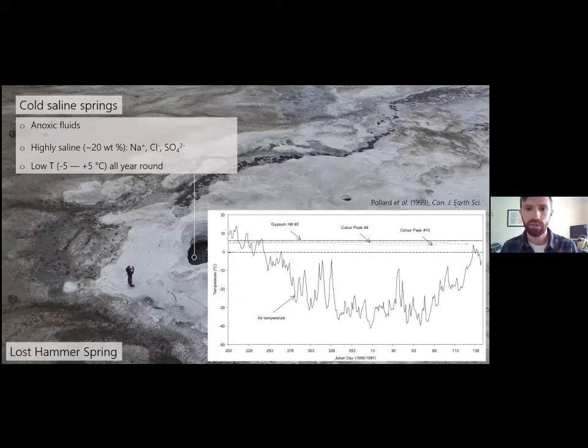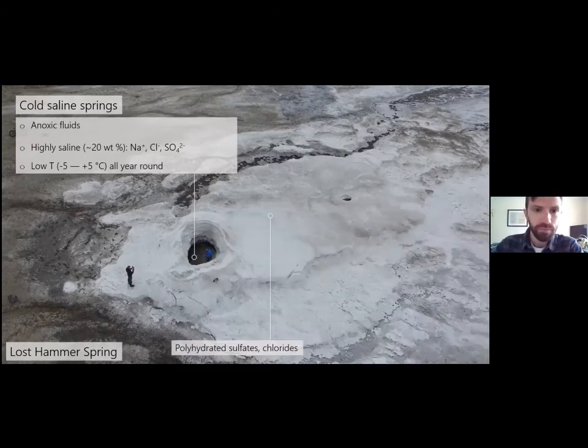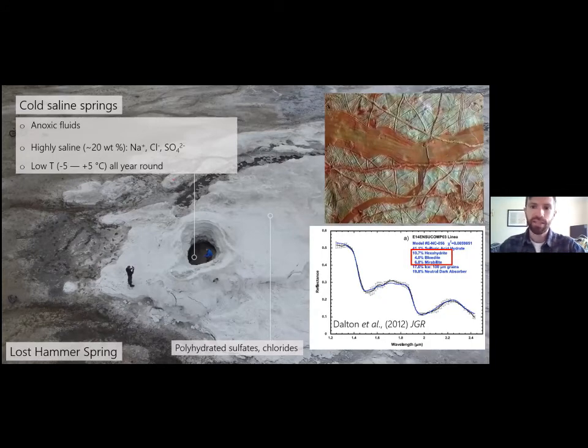The bottom line on this plot shows the Arctic air temperature, which gets as low as minus 40 C in the winter, but the spring temperatures remain constant and they resist freezing because of these high levels of salt. And the salts themselves are what caught our attention initially. These are polyhydrated sulfates and chlorides, things that are very much low temperature phases and have been implicated repeatedly in remote sensing data as major components of Europa's non-icy material.